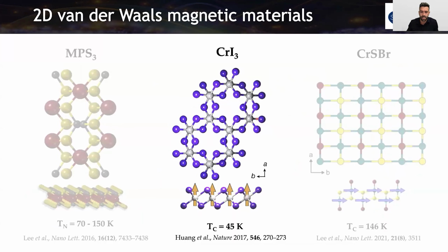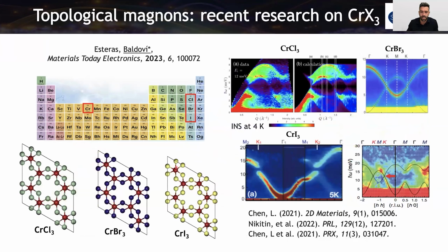Then we have also been studying chromium iodide three. In this case, it's interesting because it has a ferromagnetic honeycomb lattice, and this provides in the magnon dispersion Dirac dispersions that can also have a gap opening that leads to topological magnons in these systems. This has been experimentally measured. In the case of chromium chloride 3, this is a Dirac cone, there is no gap. This material has less spin orbit coupling, and the TC is around 13 Kelvin. It's also important in this case that the spins are in plane, something characteristic of this material.